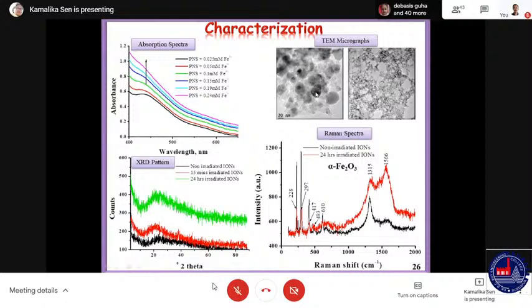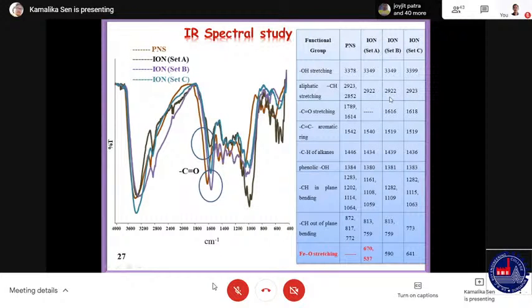We can see that before irradiation and after irradiation, the particle size has reduced. After irradiation, the particle size actually reduces because in presence of the energetic beams, the particles do not get the preference to agglomerate very easily. That is why the particle size is generally less if it is prepared in presence of irradiation.